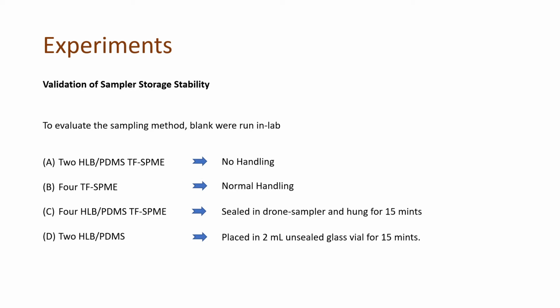Two membranes were used as a blank with no handling, and this is taken as a reference. Four membranes with normal in-lab handling were taken, and four membranes that had been sealed in a different drone sampler were hung outside for 15 minutes. Two more membranes were placed in 2 ml glass autosampler unsealed vials and left outside for 15 minutes.